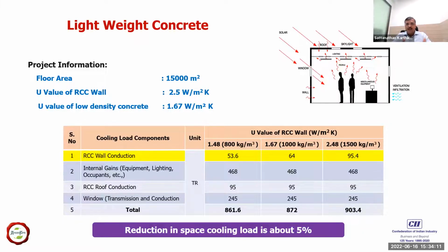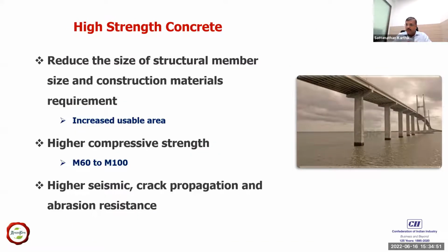So this is a case study, a comparison of a conventional RCC wall and a lightweight concrete wall. For a conventional RCC wall, the U value is close to about 2.5 watts per meter square Kelvin. Whereas the U value of a low density concrete is about 1.6 watts per meter square Kelvin. So if you do all the calculations, you will be able to very clearly reduce the heat gain by at least about 4 to 5%. You can do your calculations. You'll be able to significantly reduce the heat gain. Since it is part of the construction itself, this goes for life, and the saving is for the lifetime of the building.